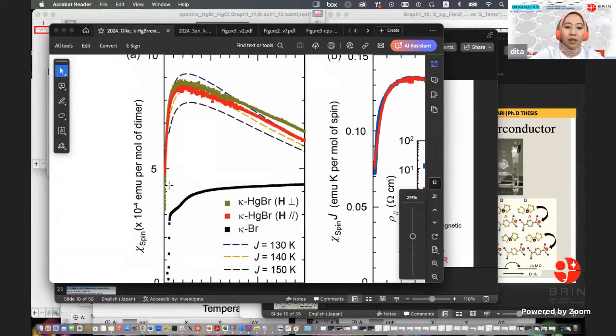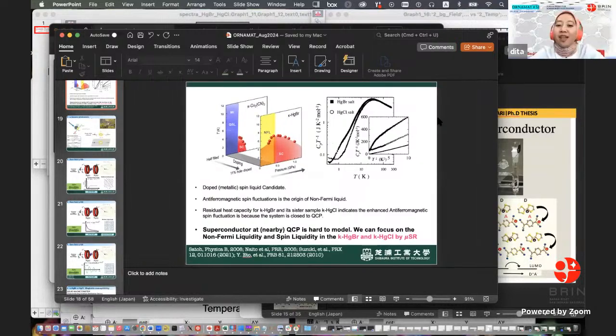Here is the susceptibility, the same as I showed. You can see this is the mercury bromide, similar to my susceptibility data. But then the other is here, on the right side. If we normalize the susceptibility data by J, the exchange interaction, you can see it is well scaled with the κ-Cu2(CN)3, which is an insulating quantum spin liquid candidate. So the spin state is maybe a quantum spin liquid, but it's very close to the non-Fermi liquid, because the charge shows that, and it's also a superconductor. Yes, it's so interesting. So that is the sense of quantum criticality.